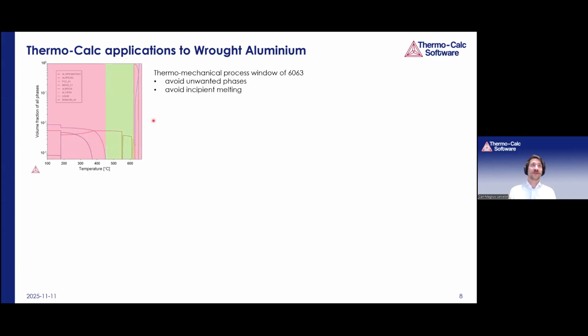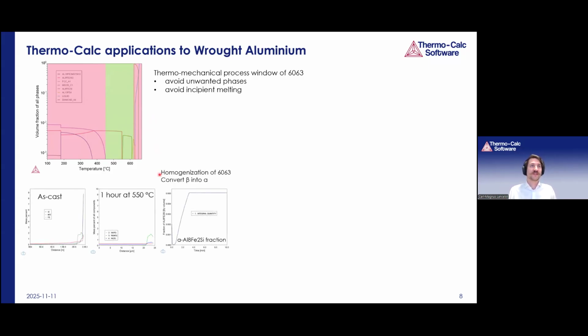And then we can have an upper temperature limit where we get melting or incipient melting of the alloy. So we have a processing window here, for example, for extrusion or other types of processing, but also for homogenization treatment. So of course, we can simulate the homogenization treatment of this alloy. And here it's interesting to convert the problematic beta particle into the alpha particle, which is a bit better for the properties. And we simulated this at 550 degrees right here, which is between the beta and the alpha phases.